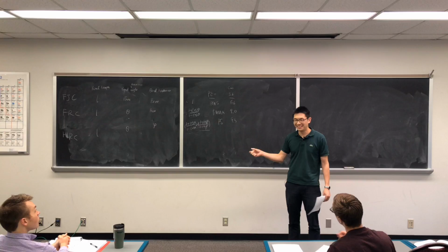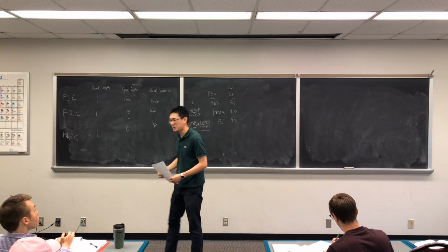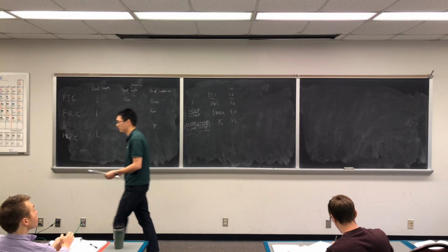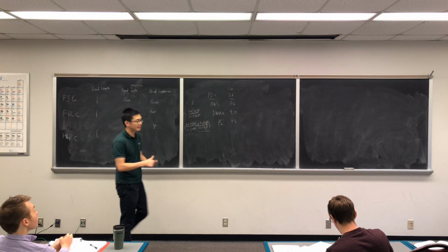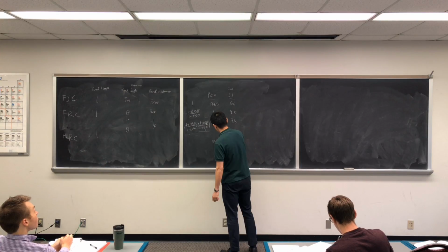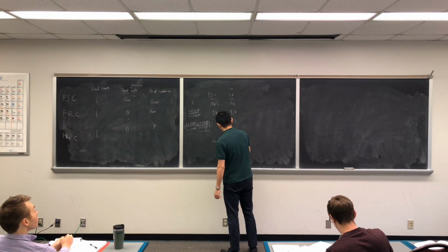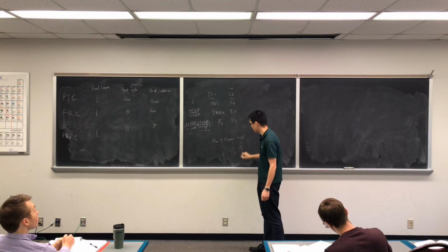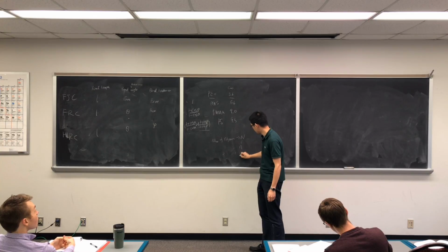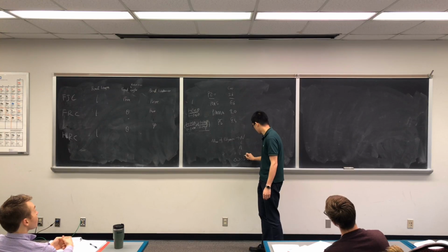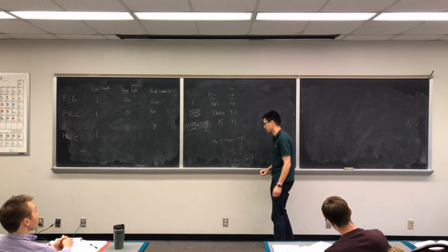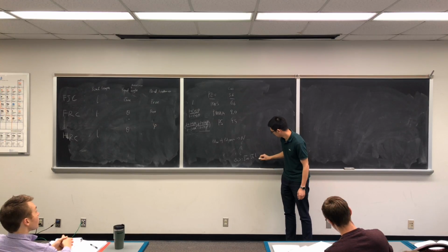how you would count, how you would get the molecular weight, and how you would estimate what's the end-to-end distance for your material, or how big the coil is in the real world, right? Because you can physically measure the molecular weight. If you know the molecular weight of a polymer, you can invert to the degree of polymerization, come down to n, and you can calculate, with the carbon-carbon bond, the end-to-end distance, right? This will be n, right?